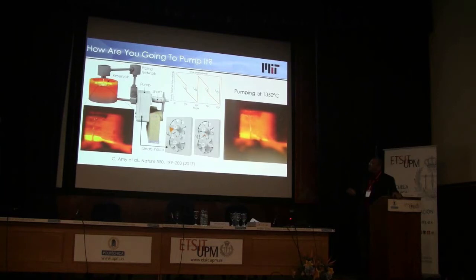One of the main things that happens in a system like this is all the components grow thermally, so you get thermal expansion. Essentially we have a bunch of hot components, and then we have a series of connecting shafts where there's a temperature gradient, it cools, and then the motor stays in the cold region. So you have a cold motor, hot moving components in the hot zone. One of the key things that happens here is you get thermal growth, and you would get misalignment of the pump, which is why, the first few times we tried it, it broke itself apart. But there's a way to account for this. If you calculate how much it grows, you can offset it so that when it heats up, it actually grows into alignment and then operates okay. We have new designs now that don't have this issue, where the growth is all axial rather than perpendicular to the rotating axis.